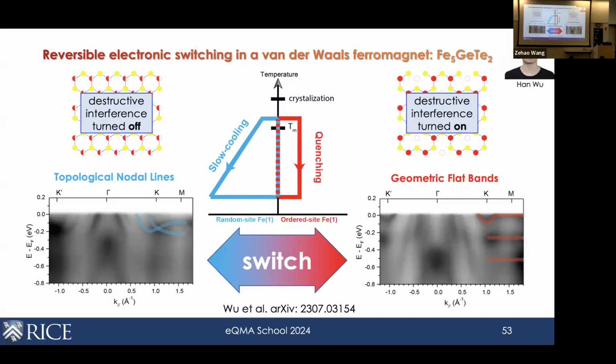But the interesting thing is that we have also demonstrated in this paper that you can switch from one state to the other by a very simple thermal method. You just gently raise the temperature above a certain temperature, and then either slowly cool it down or quench it, depending on whether the sample prefers to sit in one state or the other. We have demonstrated you can switch from one to the other in this situation. So this is actually quite an interesting material that we're working with.